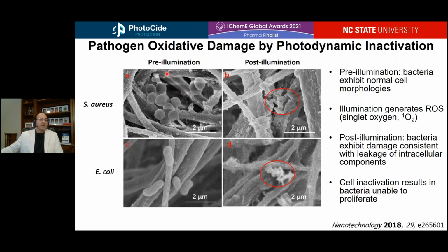antimicrobial coating. Here on the left-hand side, you can see that prior to the addition of visible light, these images were obtained by SEM for materials that were kept in the dark. You can see Staphylococcus aureus as a gram-positive bacterium and E. coli as a gram-negative bacterium exhibit healthy cell morphologies.